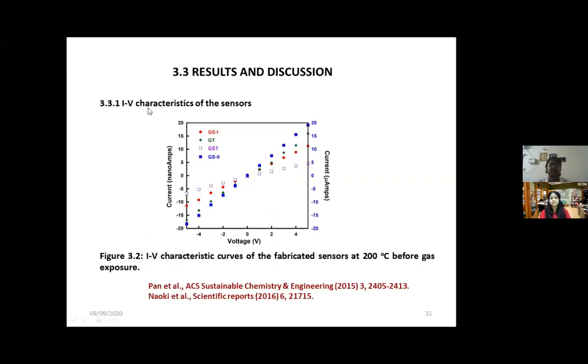So the first one is IV characteristics. We really wanted to ensure that the coated sensor material, the substrate and the gold electrodes are intact. What if it comes off? So for ensuring that, we go for IV characteristics. IV characteristics we performed at 200 degrees Celsius with a voltage ranging from -5 to +5. So we observed a linear response, which tells us this is ohmic. So ohmic response, that is linear response, indicates that these sensors are in good condition, that is, the electrode, sensor material and the substrate are intact.